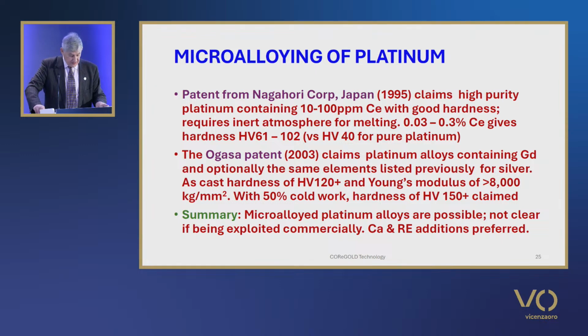A platinum cerium phase diagram shows characteristics similar to that of the gold cerium system. For cerium contents of 0.03 to 0.3%, hardness values of 60 to 102 were obtained compared to 40 Vickers for pure platinum, and hardnesses of 120 to 136 for 950 fineness platinum alloys. A commercial alloy UHP platinum from Japan appears to be a microalloyed platinum at 999.5 fineness, but little information is available.